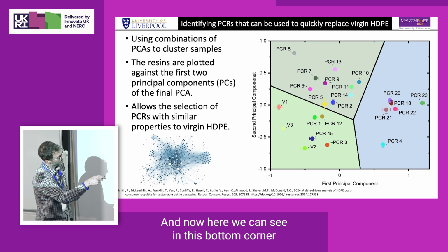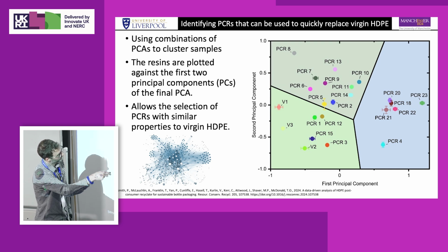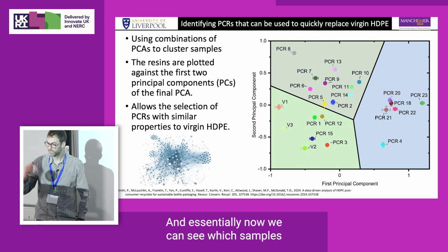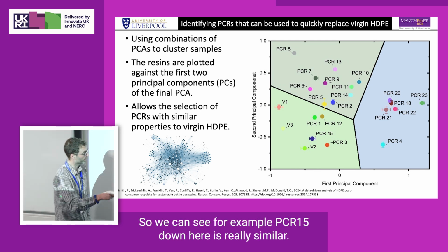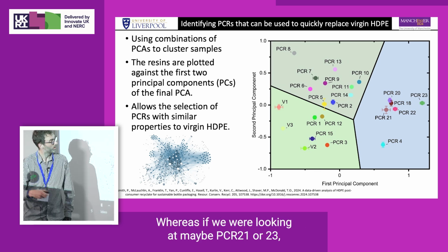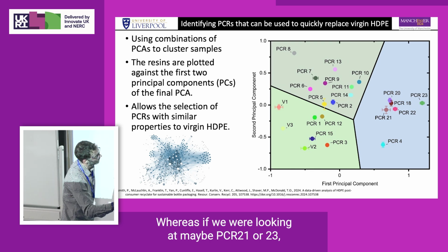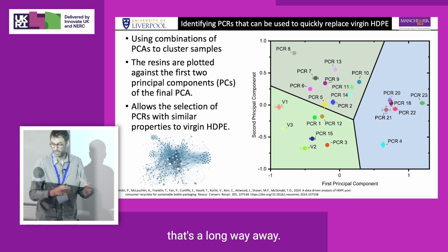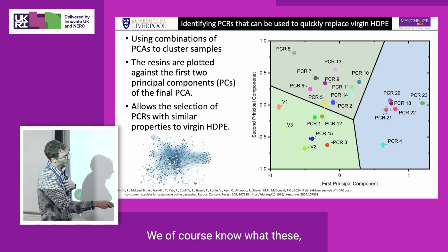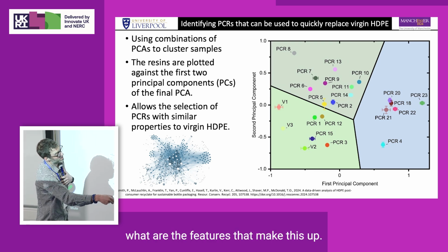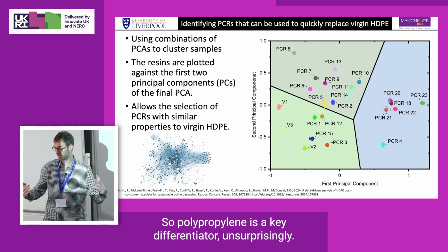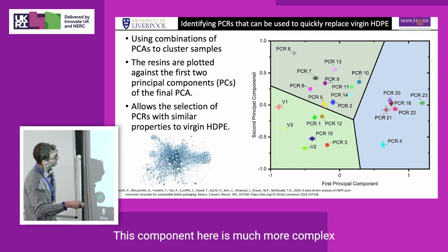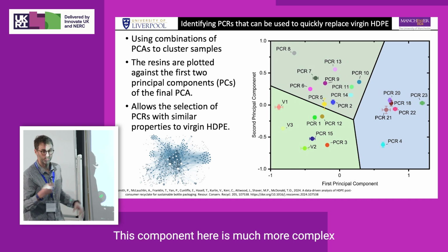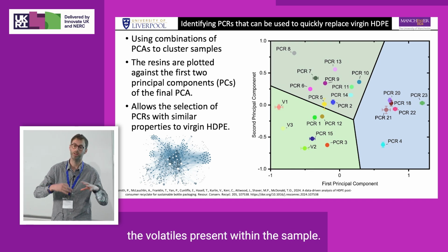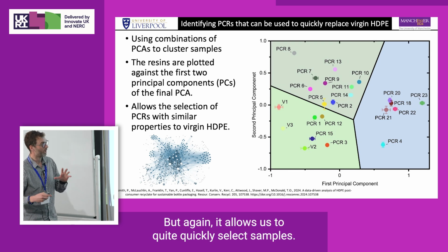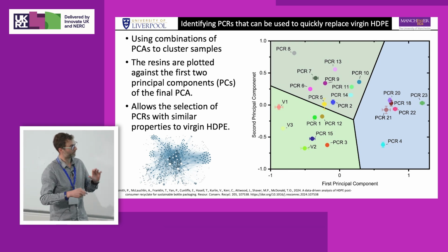And now here we can see in this bottom corner are 3 virgin samples. And essentially now we can see which samples are most similar to virgin. So we can see, for example, PCR 15 down here is really similar, whereas if we were looking at maybe PCR 21 or 23, that's a long way away. We of course know what are the features that make this up. So polypropylene is a key differentiator, unsurprisingly. This component here is much more complex and contains information about rheology, the volatiles present within the sample. But again, it allows us to quite quickly select samples.